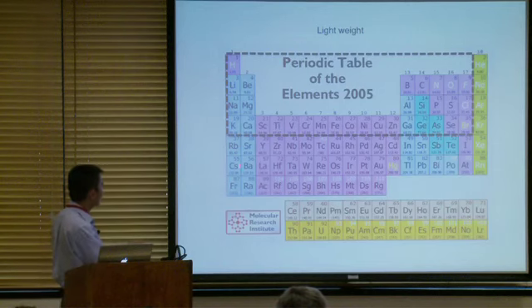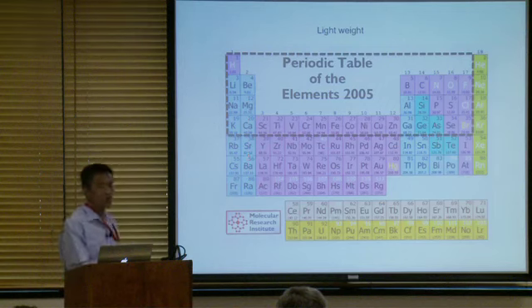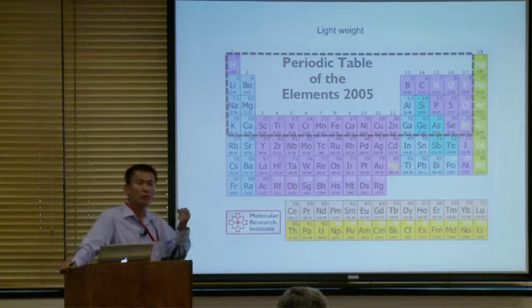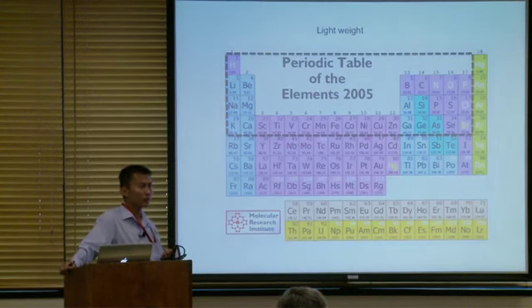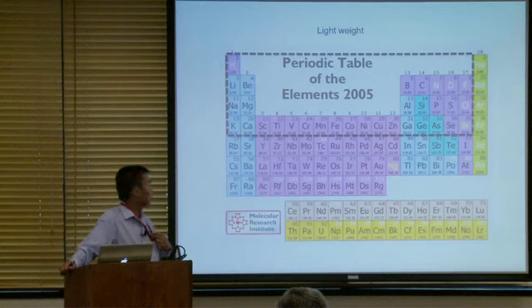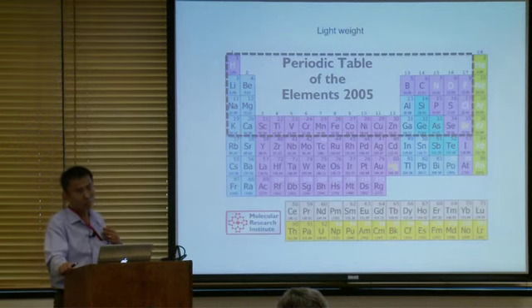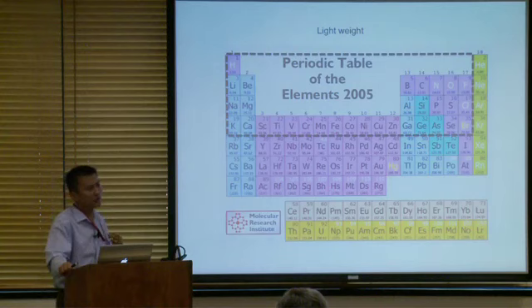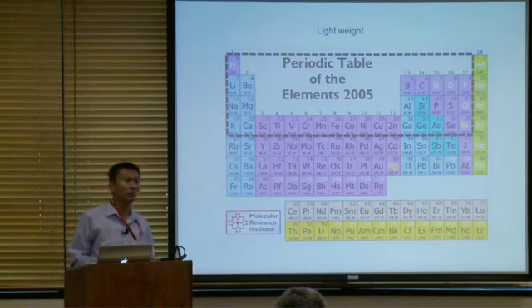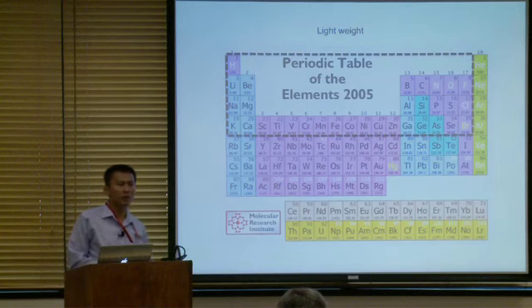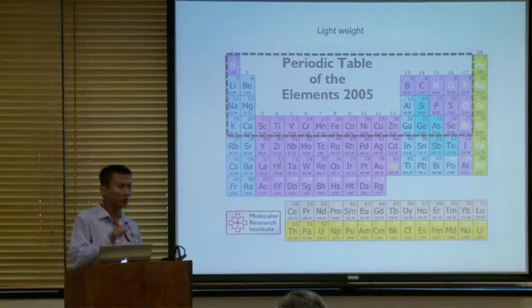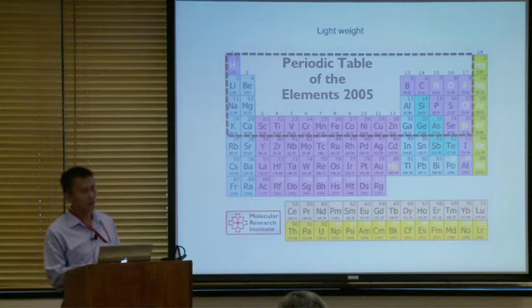If you go down right here, that's too big. And let's look at Mg, magnesium. In a 2+ state, it's also very small, right? With the 2+ oxidation state it becomes a cation, and it's very small. But unfortunately, because magnesium is in a 2+ state, the electrostatic interaction with the environment is too big. So magnesium moves so much slower compared to lithium. Lithium has only one charge. With a lower charge, they move faster. They don't interact with the surroundings that strongly.